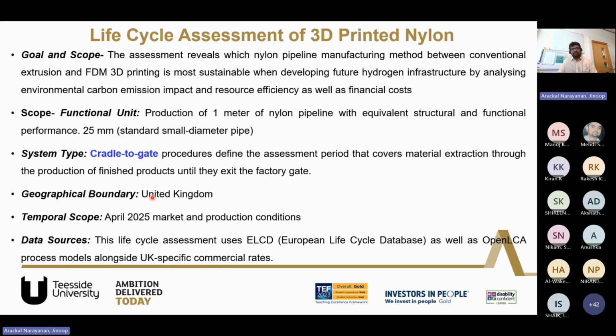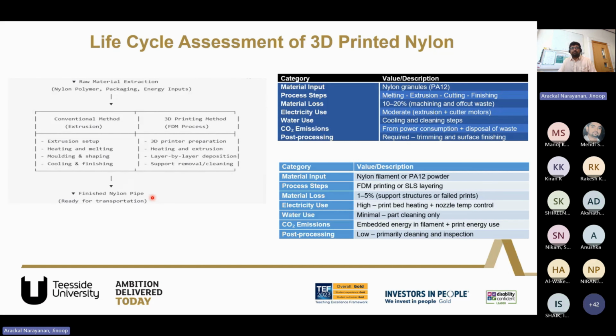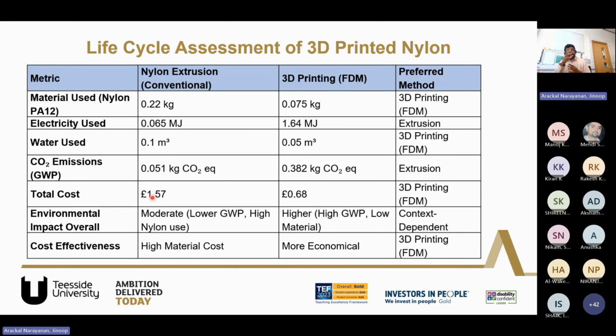And we did a life cycle assessment as well, a quick life cycle assessment from cradle to gate, and we compared a conventional nylon to 3D printed nylon and how it can be beneficial for a transportation application. And we could see that in terms of material usage, 3D printing is better, but in terms of the energy usage, conventional extrusion is better. In CO2 emission also, if you consider the filament and the overall life cycle, extrusion is better. So if you consider the environmental impact, it again depends on the context. So it's moderate for extrusion, slightly higher for 3D printed nylon. This is our initial assessment. We are still working on it to develop a full-scale model on life cycle assessment of 3D printed nylon.